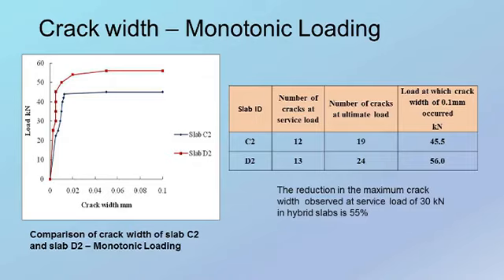Actually, the slab is kept this way. This is the tension face of the slab. We can see numerous cracks on the tension face, but the crack width was less. Under monotonic loading, the load at which a crack width of 0.1 mm occurred was 45.5 kilonewton for slabs without fiber and 56 kilonewton for slabs with fiber. This graph indicates the load and the crack width which occurred at various loadings.